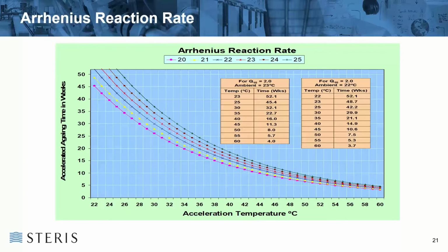If you change the ambient temperature in the calculation again to 22 degrees, at the 60 degree level you're down to 3.7 weeks. So again, it's a saving in the time in the project. However, that brings additional risks into place as well, which we need to be able to take into account.